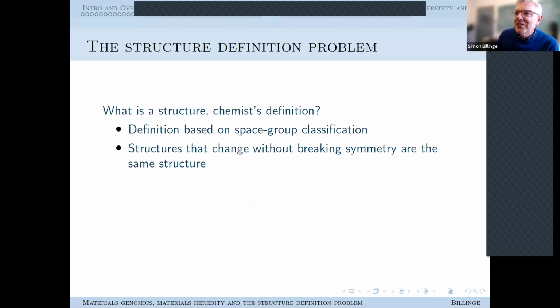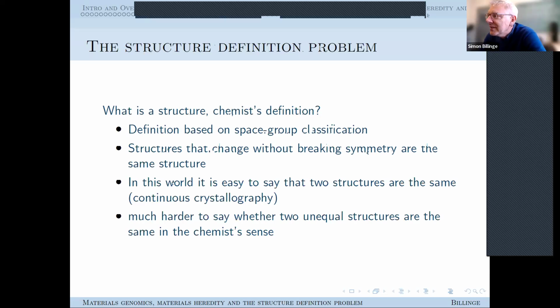So there's also the sociological definitions, which is something to do with what chemists think. So what's a chemist's definition? I actually tried to use Wikipedia to find their definition. And when you go to crystal structure on Wikipedia, it just starts telling you crystallography. It doesn't say what the definition of a structure is. So maybe in some chemistry textbooks it's there. But basically, the chemists take this crystallographic view. They define a structure based on the space group classifications. So they say structures that change without breaking symmetry are the same structure. But as soon as you break symmetry, you have a new structure.